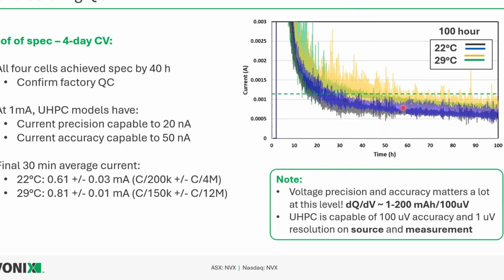So when we looked at this data, we said, okay, great. The 30-minute average current at the end of this is C over 200,000. And then the variability between those two cells is plus or minus C over 4 million. These are odd numbers to be throwing out. We don't necessarily think of C rates like that, but it's maybe more relatable and transferable between cells than the actual magnitudes of the current.